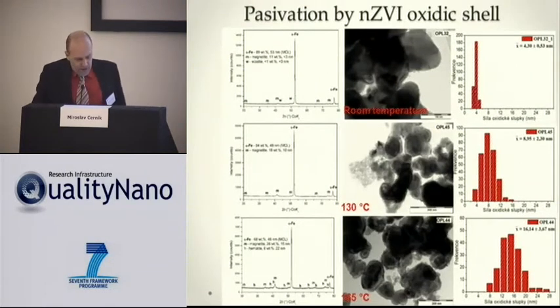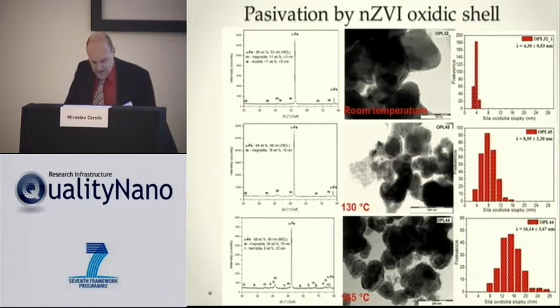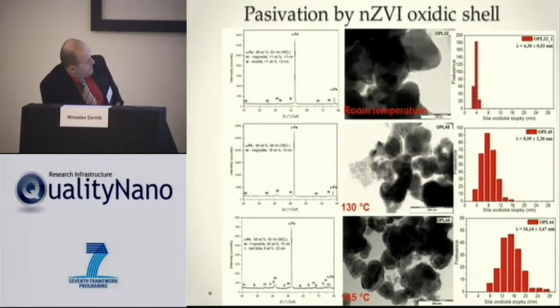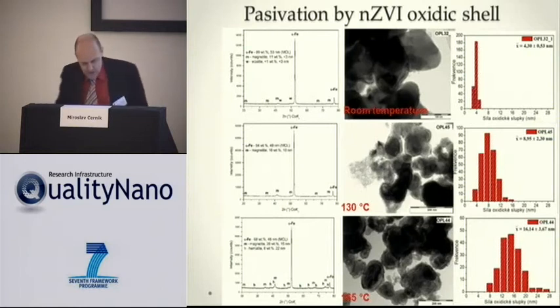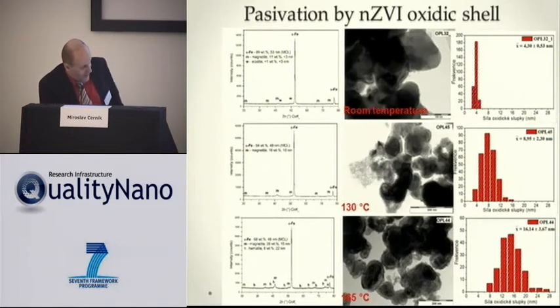The surface passivation by the oxidic shell can be done by different conditions, and I have here an example of 3 different conditions: oxidation at room temperature, 130 and 165 degrees, and you have the pictures of how the particle looks. They are not different. On the left side you have the Röntgen spectra of contents of the iron and iron oxide, and you see that the peak of the iron is the highest in all cases, so that most of the material is still zero-valent iron.